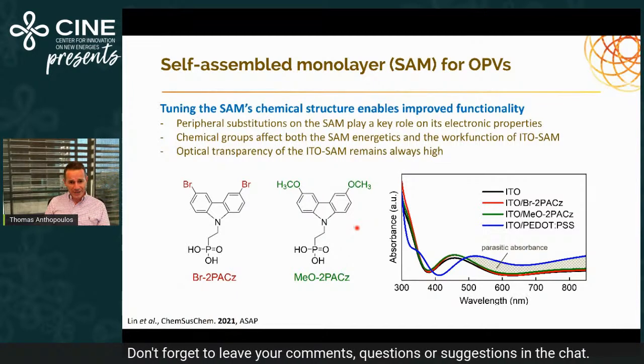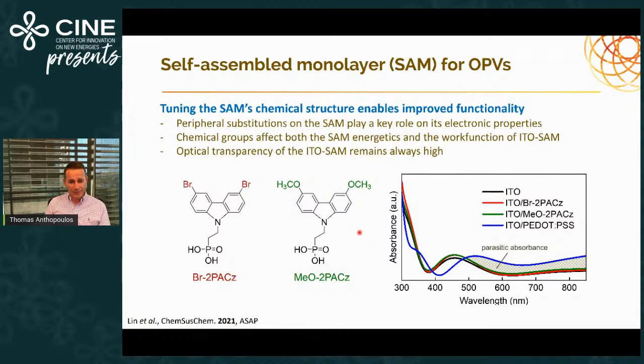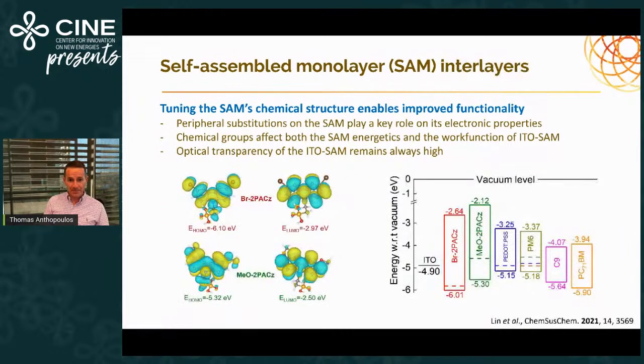Such a control over an interface we never had before. We were always relying on thin solid films where we knew very little. We know very little about the surface properties of PEDOT:PSS because it's not really a structured material. We don't see a very regular pattern. Now we have a self-assembled monolayer that forms and interacts with specific sites on the surface of the ITO electrode. The challenge now is to understand what exactly is important in this interaction. We're working intensively on this topic as we speak. We can also change the conjugated unit from carbons to something else.